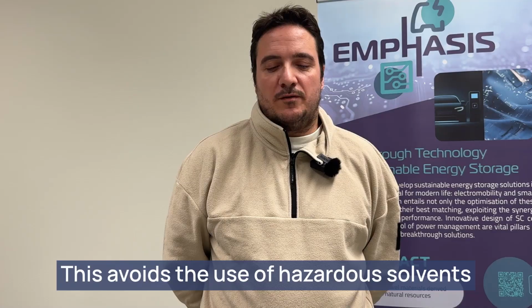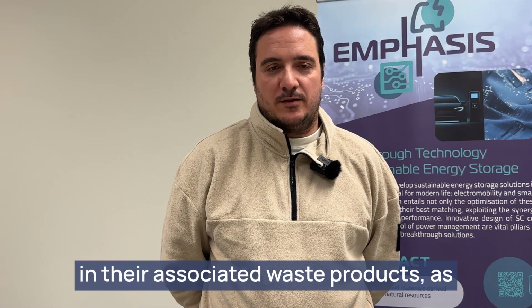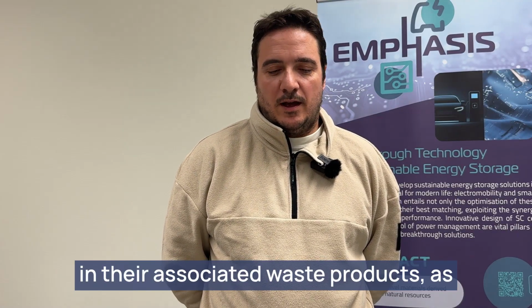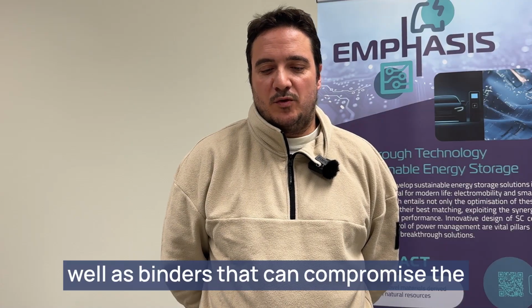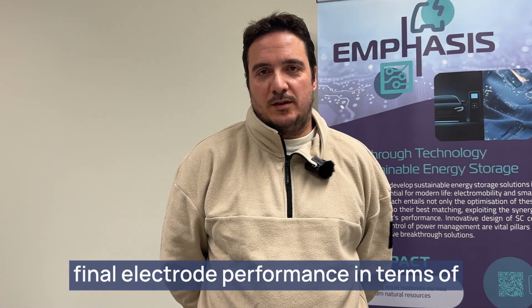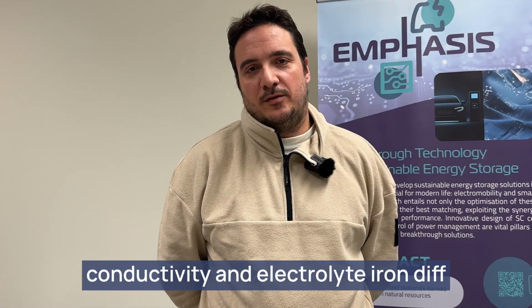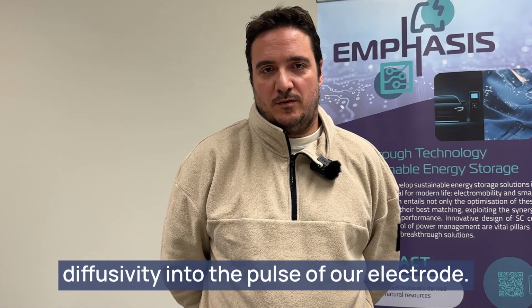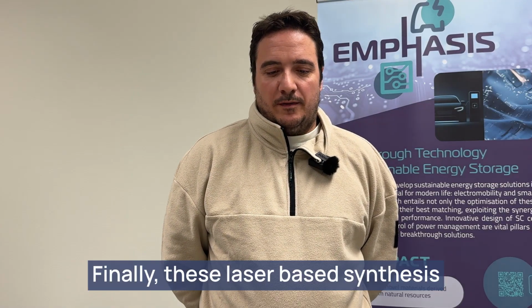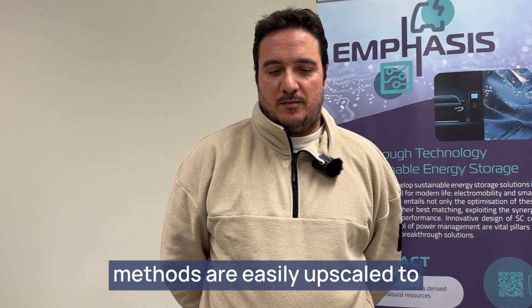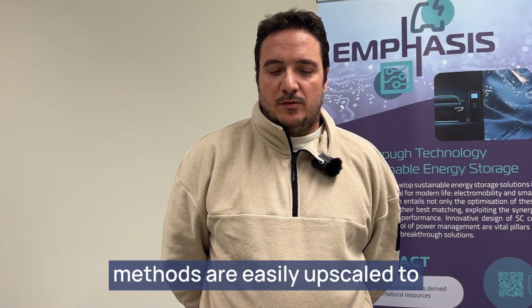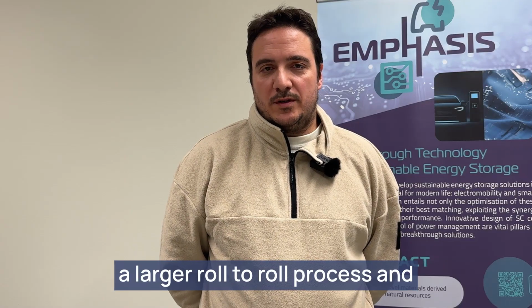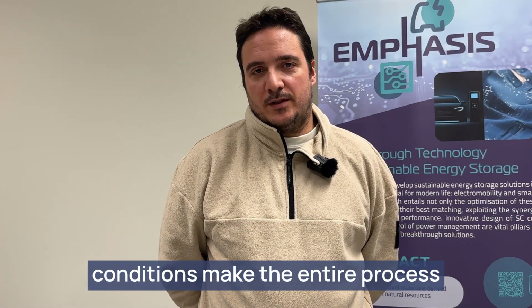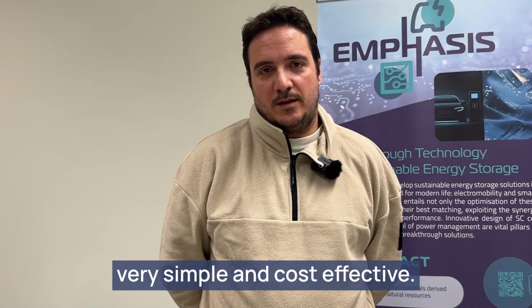This avoids the use of hazardous solvents and their associated waste products, as well as binders that can compromise the final electrode performance in terms of electronic and electrolyte ion conductivity and electrolyte ion diffusivity into the pores of our electrode. Finally, these laser-based synthesis methods are easily upscaled to a larger roll-to-roll process and can take place under ambient conditions, making the entire process very simple and cost-effective.